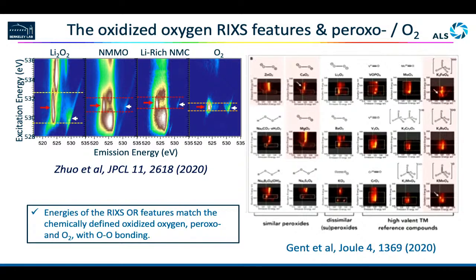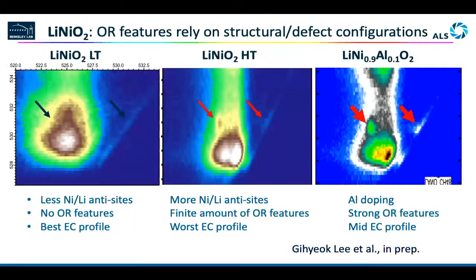And then if you compare these RIXS features with those of peroxo or oxygen gas, but not the superoxo species, superoxide shows up at a completely different position in energy. So it seems like they do take exactly the same excitation and emission energy. That indicates the feature we see seems to be an O-O bonding formation, meaning it's a chemically defined oxidization of oxygen, not physically.